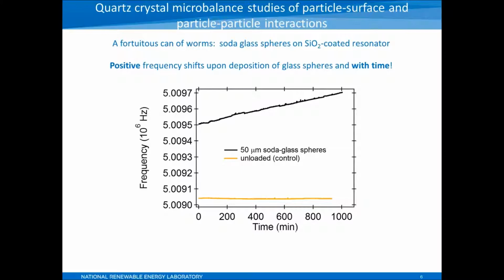There's two things about these results that were initially very puzzling. When we put the soda glass spheres on top of our resonator, we see a positive change in the frequency. It's as if the quartz crystal got lighter, as if it lost mass, which I did not understand. The other thing that was puzzling to me was a fairly large drift over time, although this is something that we saw with the Arizona road dust.